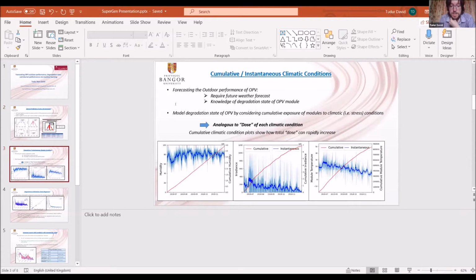However, in order to be able to predict and forecast the outdoor performance of OPV modules more fully, we also need to be able to understand both the performance of the devices as a function of the daily weather conditions and also the degradation of the modules. So in order to model the degradation state, we have considered the total exposure of the modules to different climatic conditions, as well as the instantaneous daily weather conditions. So this can be considered analogous to the dose of each climatic condition. So the graph shown here illustrates how different climatic conditions can accumulate over time, despite the instantaneous values decreasing or remaining relatively stable.